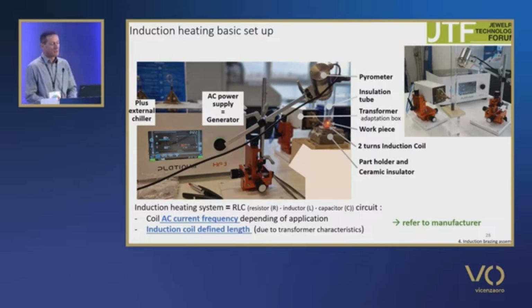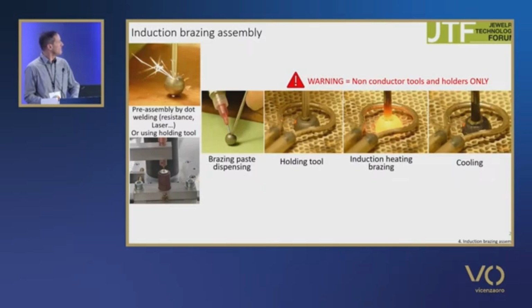There are some key points to refer to the manufacturer about the AC frequency and the induction coil length. The induction brazing assembly starts mainly with a holding tool, or pre-assembly with induction, laser dot or resistivity pre-assembling. After, you have to dispense the brazing paste, put it in the holding tool, heating and cooling.